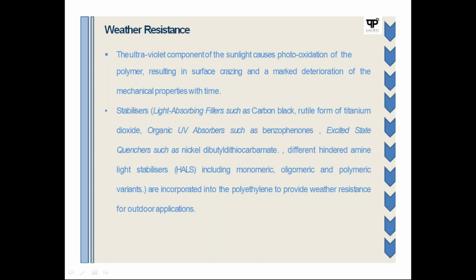So one of the main important factors which should be seen at the end of compounding is the process parameters, especially if we prefer to go for a twin screw extruder while dispersing this carbon black and non-black UV stabilizers. It is always helpful to maintain the good quality of the weather resistance of the product.